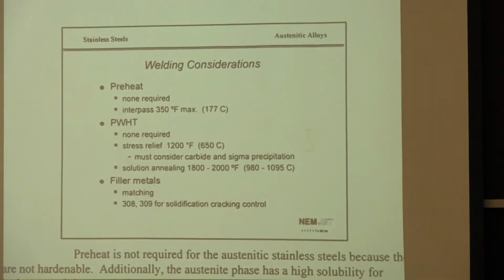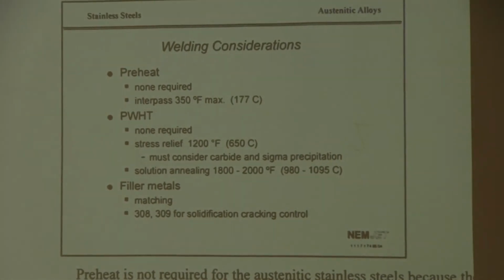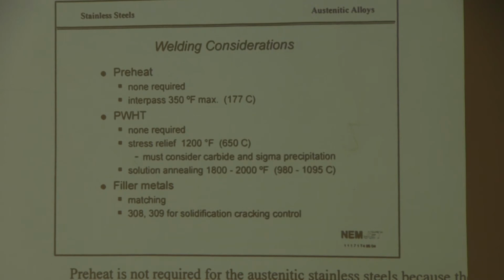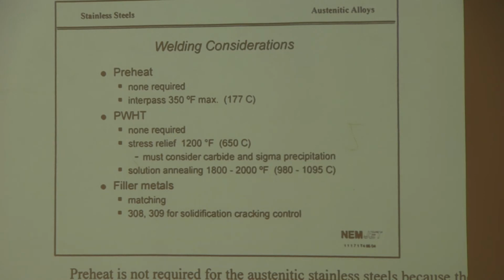Some things to consider when you weld austenitic stainless steels: because they don't precipitate, they're not hardenable, basically. There's no need to preheat them. And it is important, because of the phases that can form, that you do watch the interpass temperature if you're doing multiple welding passes on the austenitic stainless steels.